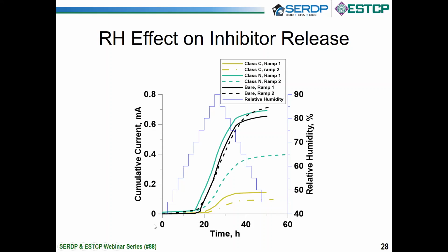So it orients you to this slide. This is time on this axis. It's a cumulative current. So again, for each point of time, we added up the currents and then added them for the cycles. On this axis, you see the relative humidity. Here's the relative humidity cycle we did. And we actually ran 2 cycles. So to make this easier to understand, both of those cycles show up on this plot. And I'll talk about each one individually.